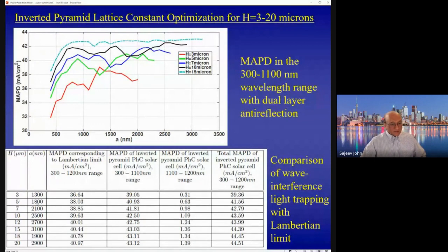Here's a summary of the photocurrent densities, optimum lattice constants, and the Lambertian limit for this range of silicon thicknesses ranging from 3 to 20 microns. So again, for 15 microns, the optimum lattice constant is 3.1 microns, and the Lambertian limit would predict that the maximum photocurrent density in this case is slightly over 40 milliamps. In our case, based on solution of Maxwell's equations and wave interference light trapping, we find that in the 300 to 1100 nanometer range already 43 milliamps, and an extra 1.3 milliamps in the 1100 to 1200 range, leading to slightly over 44 milliamps per square centimeter.